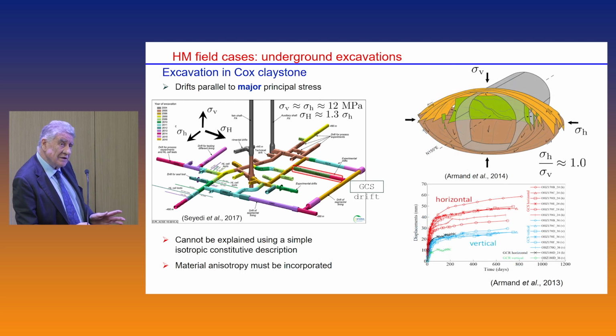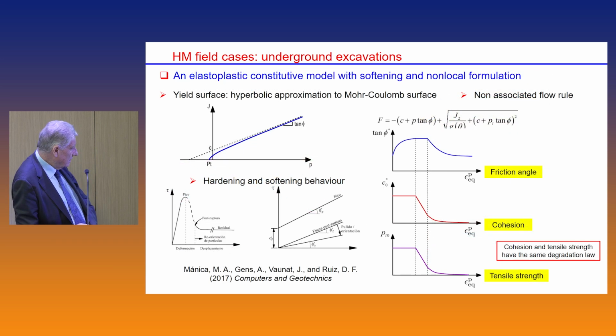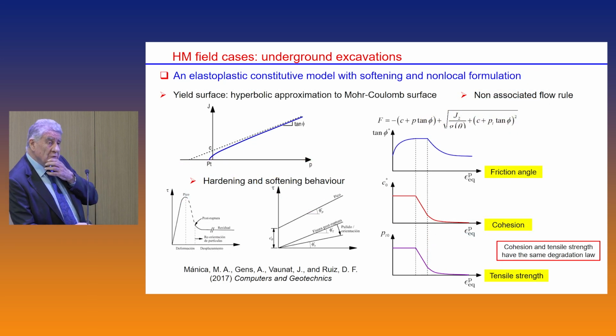If we now take excavation in the perpendicular direction, this is now parallel to the major principal stress. So now in a cross section we have something which is more or less isotropic in terms of in situ stresses. But as you can see, the development of the EDZ, the excavation damage zone, is certainly not isotropic. It develops a lot horizontally, only a little vertically. And again, now we have horizontal convergence larger than vertical. Okay, so we are going to try to model the development of this EDZ.